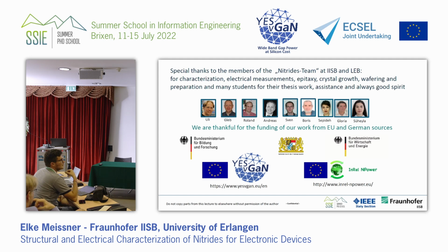Thank you for your interesting talk about defects. Something very interesting to me is the V-pits. You introduced that this might be a source for the current leakage. In my growth, I also observed very typical V-pits, but I don't know what the reason is. You said this appears in the nucleation layer, and it's also in my nucleation layer. Could you please explain what might be the reason for the generation of the V-pits?